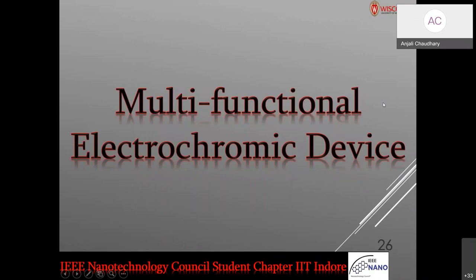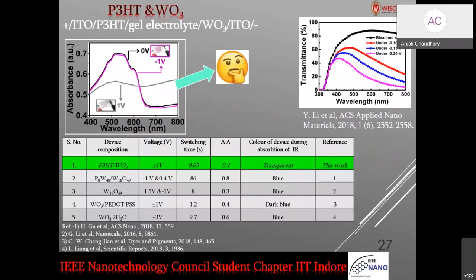And next is multifunctional electrochromic devices. When we did our experiment using P3HT, we found that in this region, 700 to 800, which is very close to the near IR radiation, in the transparent state it is absorbing some near IR part. So can we increase this fractional amount of absorbance using P3HT while not compromising on its visibility?